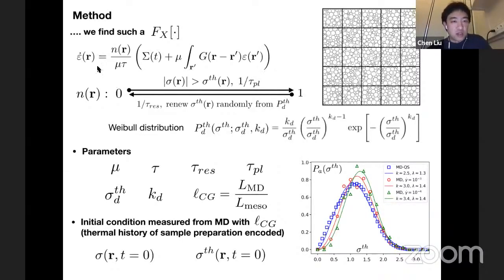It's quite simple. The local shear rate is just linearly coupled with the local stress, but we introduced a local state variable that alternates between 0 and 1. When it's 0, it means that locally there are no plastic events, and when it is 1, a local plastic event takes place. The local plastic event is activated when the local stress is larger than a certain threshold, with a rate of typical time scale that we call tau plastic, and it can become elastic from the plastic state at a rate of a typical time tau reconstruction.